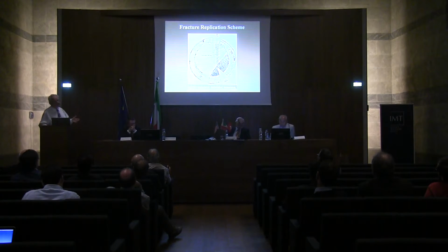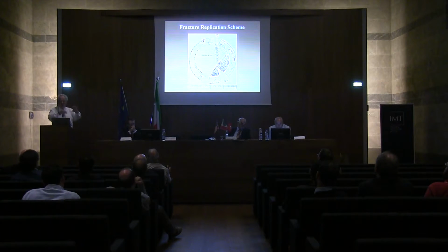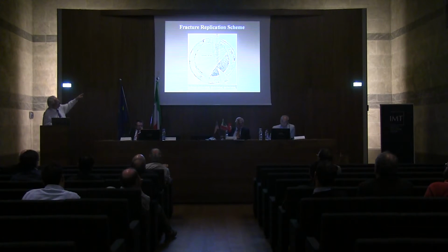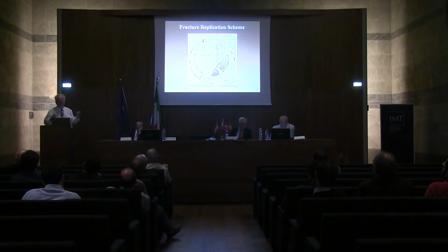Now, here is a schematic that I created when I got the actual fracture piece. The head broke off. That outer band around is the larger head and the marks in the galvanized coating. The actual pin diameter is that solid circular part inside that. And you can see up at the top is where the man cut the sample out, where he did some metallography looking at the origin. And so I don't have the actual origin. And at the bottom, we got the final rupture zone. And those lines on the fracture at the top are the clamshell or beach marks for the fatigue crack growth. And the rough area on the lower right, that's the final rupture zone.